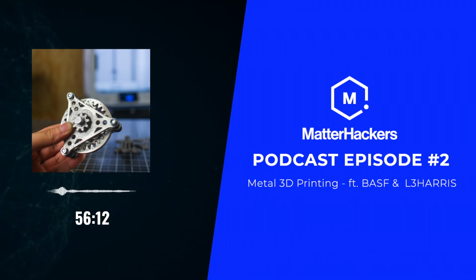You mentioned it briefly, but cleaning it up as a green part is much easier than cleaning it up as a stainless steel part when it comes back. Yes, you do not want to be doing significant processing of the part once it's been sintered. Which is totally doable. You can machine it, you can grind it and all these things, but removing layer lines is easier done in my clay analogy than it is in the hardened steel analogy. Yes, and unless you're planning to machine this part down on a CNC or manual lathe or mill, then you do not want to be doing any cleanup after it's sintered.